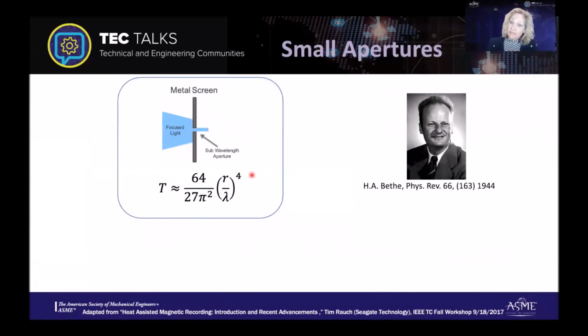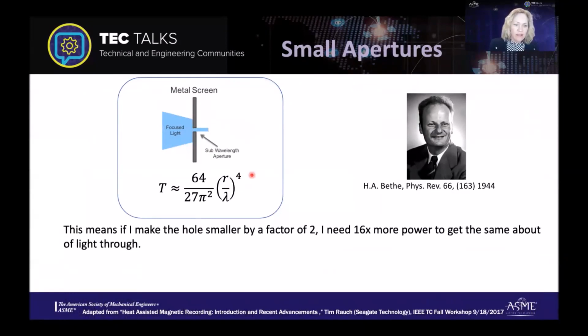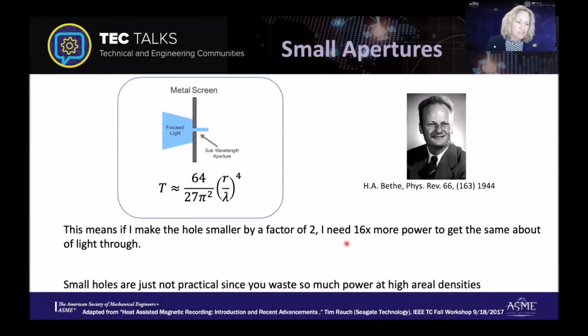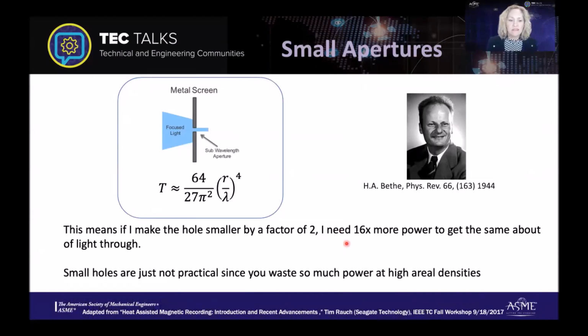So if we're going to start scaling this type of technology, and I want to increase the areal density, so I want to make that hole smaller, if I make it smaller by just a factor of 2, I would need 16 times more power to get the same amount of light through. And so this just isn't a practical solution. You'd need too much power as you try to go to higher areal density. And not just that power is wasted, but also that power you're not using is going to translate into heat in the head, which also could cause reliability problems. So this is not a solution for us either.